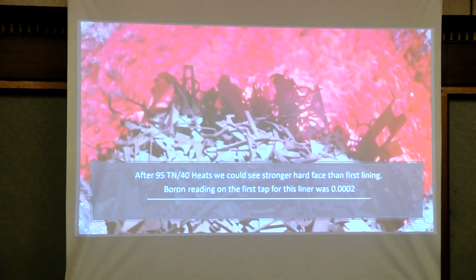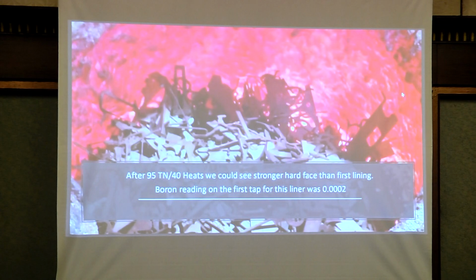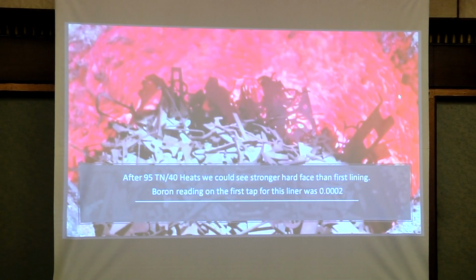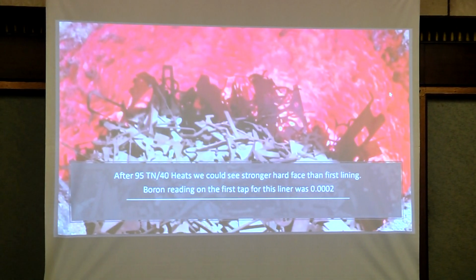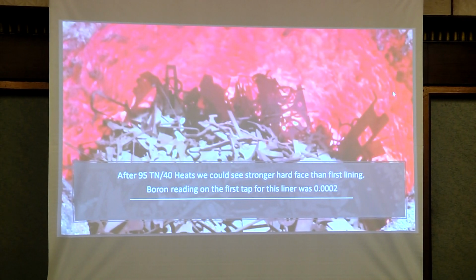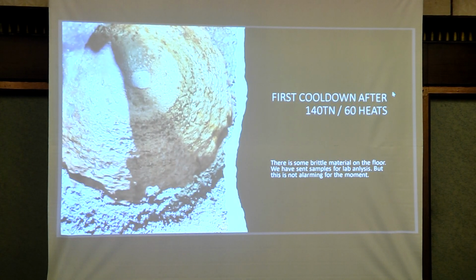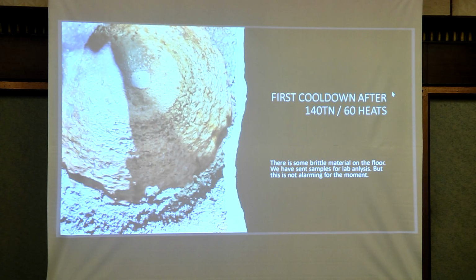After 95 tons or 40 heats, we could see a stronger hot face than the first lining had. Boron reading at the first tap was 0.0002. First cool down after 140 tons, 60 heats, there was some brittle material on the floor. They've sent samples to be analyzed, but again, it was nothing alarming. The lining could run a lot more time.